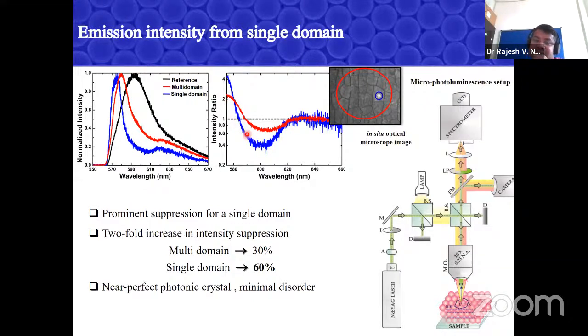It's around 60% we got from a single domain. And this is a precise measurement, which actually helped us in doing these nice measurements. Otherwise, people believe these samples are not that good for this kind of experiment, largely because of the inherent disorders. And second is the very low index contrast of the sample, because these samples are made of polystyrene or polymethyl methacrylate spheres, which have a very low index.